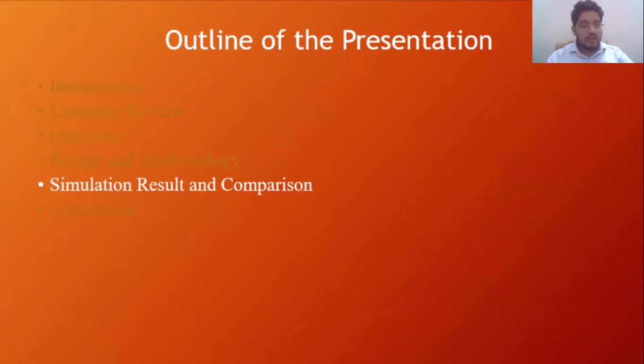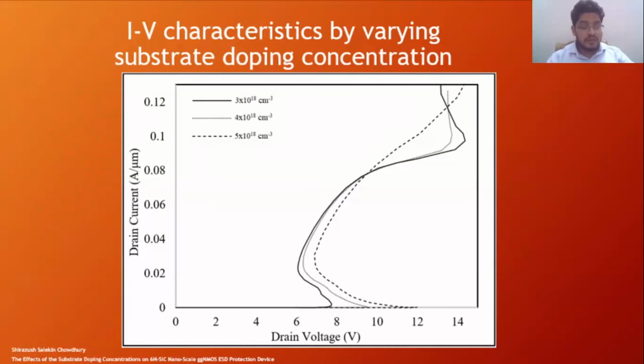Simulation results and comparison. Three different substrate doping concentrations are used. The source and drain doping concentration are chosen as 2E20 per cm cubed. The figure shows that for higher substrate doping concentration, the trigger and hold voltages are higher. For the substrate doping concentration of 3E18 per cm cubed, once the drain voltage is increased to around 7.75 volts, the base-emitter junction of the parasitic BJT becomes forward biased and turns on, and consequently snapback occurs. The hold voltage for the substrate concentration 3E18 is 6.08 volts.